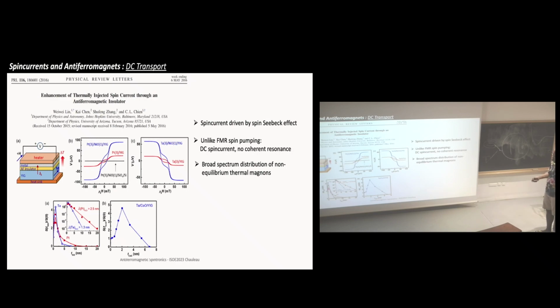Here you have the detector, as usual. If there is a spin current which enters there, it can be converted to charge by the spin Hall effect, and you will measure the charge. And this is what they have done as a function of the field. And then you have a bare YIG platinum, and if you add the NiO, you can see that you also find a very nice dependence. And the nice thing is that if you put tantalum, which has the opposite spin Hall angle, it is reversed. So this is the fingerprint of the fact that it's a spin Hall related effect.